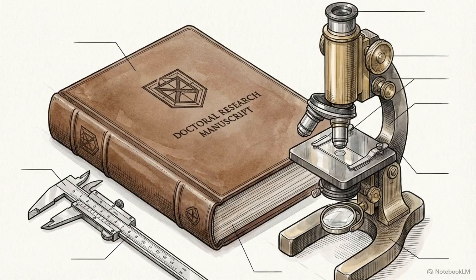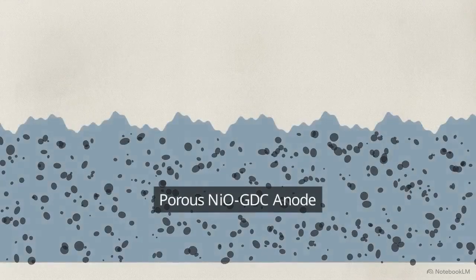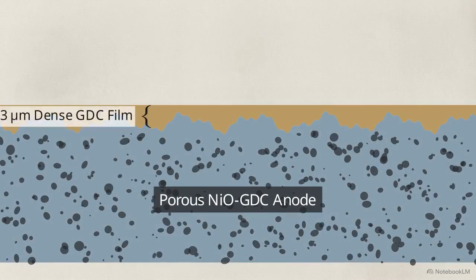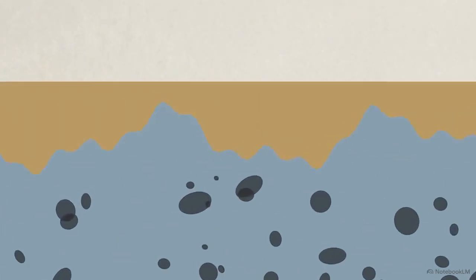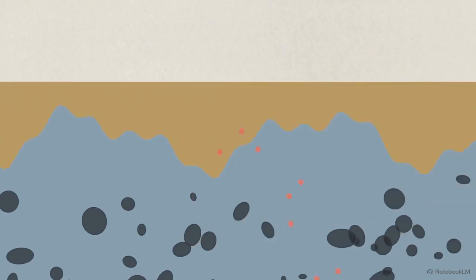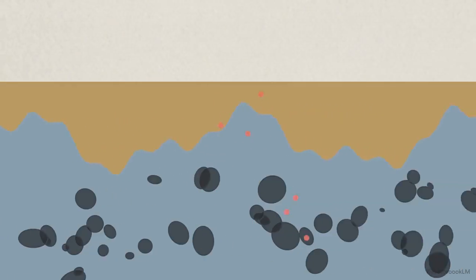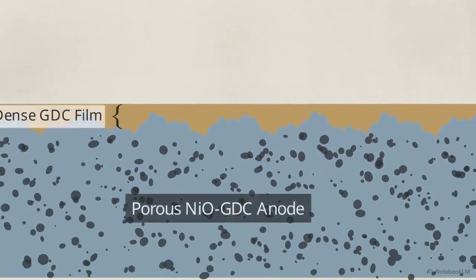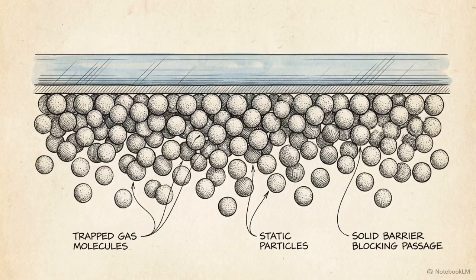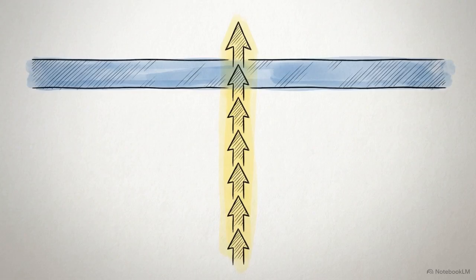Dr. Muralidhar Girish Chourashiya's doctoral research at Shivaji University targeted this exact bottleneck, establishing a methodology to reliably synthesize this complex interface. The result was a completely continuous, perfectly dense GDC thin film, measuring exactly 3 micrometers thick. This ultra-thin solid layer successfully anchors to the porous nickel oxide GDC anode below it, leaving zero structural voids where gas could leak through. At precisely 3 micrometers, the film is thick enough to maintain the gas-tight physical barrier, yet thin enough to provide the exact electrical resistance properties needed for power generation.